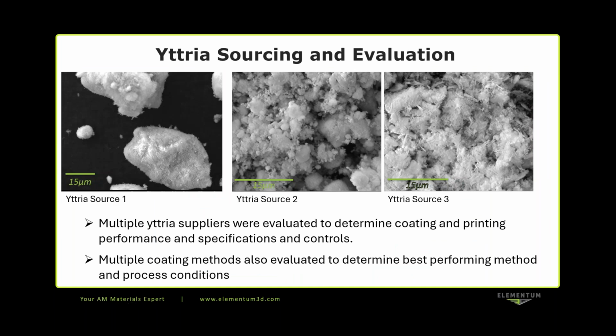A little bit on our yttria sourcing and evaluation. So you can see from these SEM images that with the nano yttria, you can get different morphologies and characteristics from different sources, different suppliers, and different lots. So it's very important that we as a producer have quality control over our yttria sourcing to make sure that we're using the right feedstock so that we get the right consistent performance. And this is something that we're continuing to do, analysis on every lot that we use, making sure it meets our quality standards.